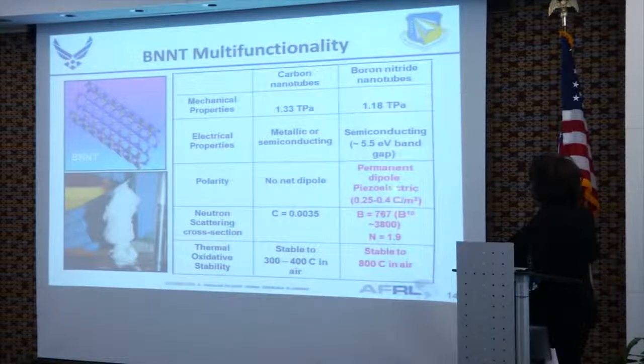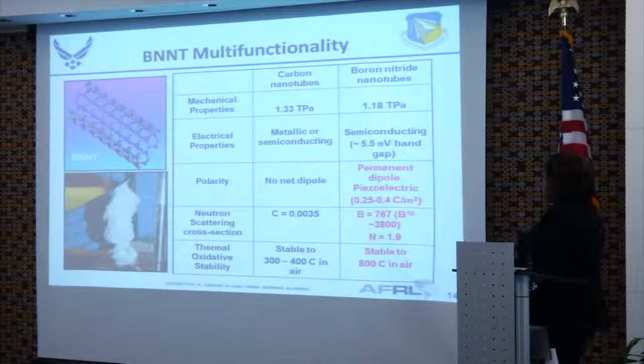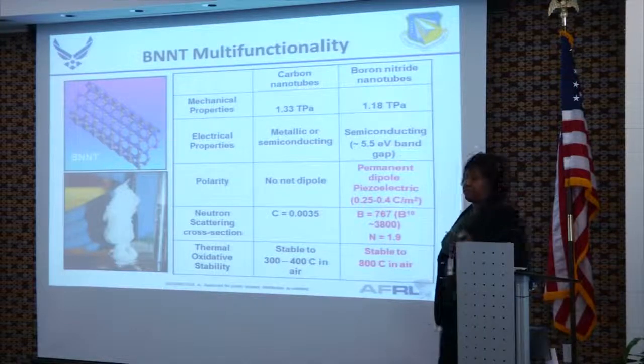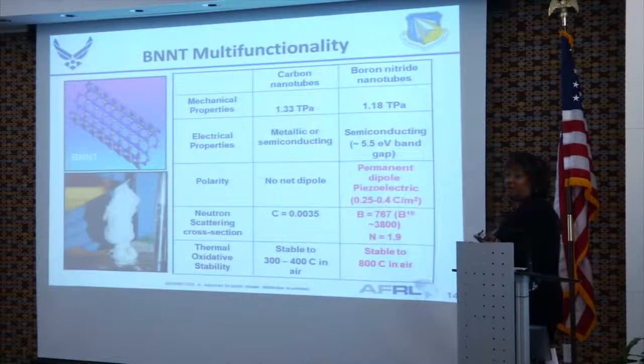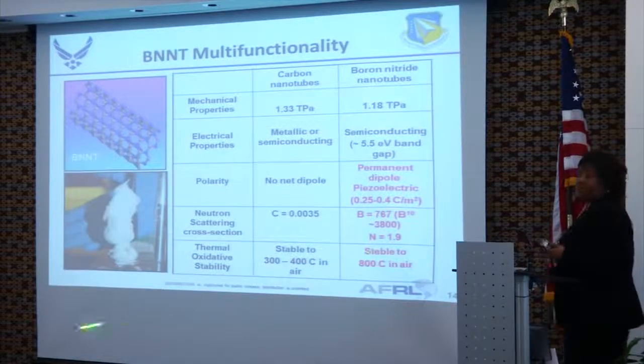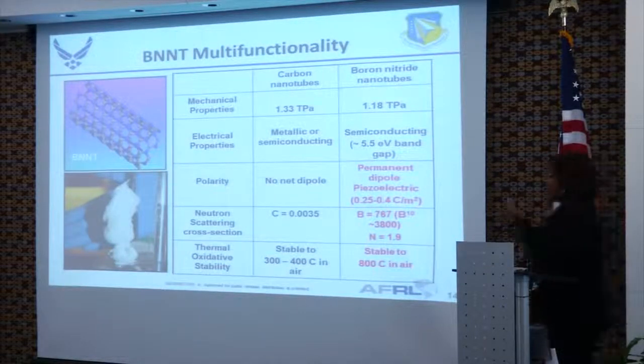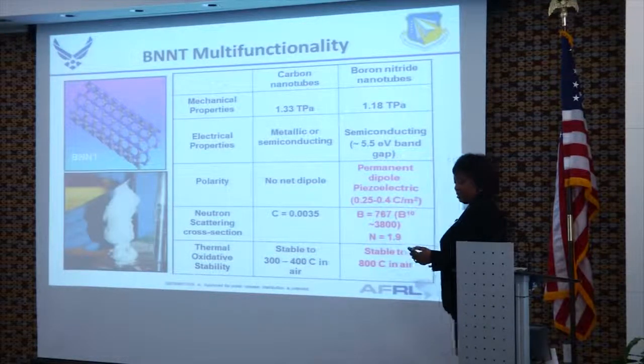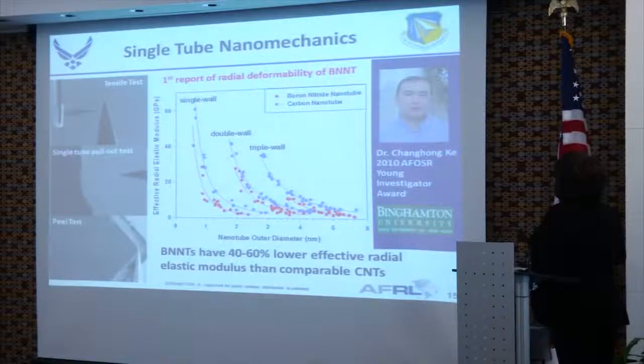They have a net polarizability, so they're intrinsically piezoelectric. Boron, we know, particularly boron 10, has a strong neutron scattering cross-section, so they're useful for neutron shielding type issues. And then also, these materials have a much higher thermal oxidative stability than carbon. And so you get up to much higher temperatures, and this will open up that temperature space for some of the needs in Air Force systems. And so again, here's work where I've tried to forge a new team to work in this area.